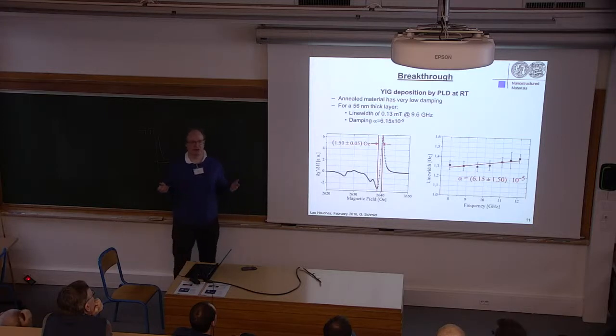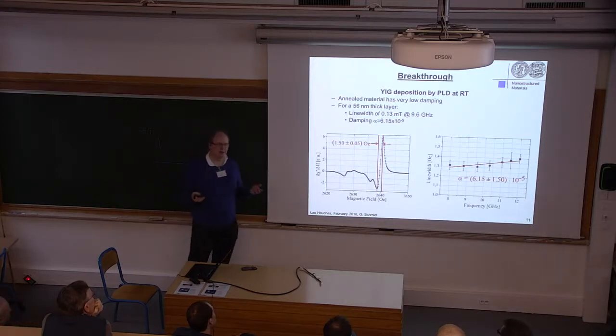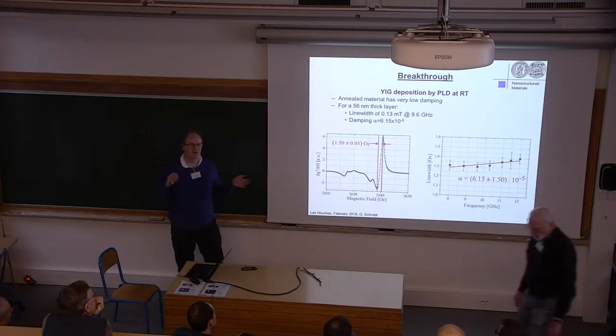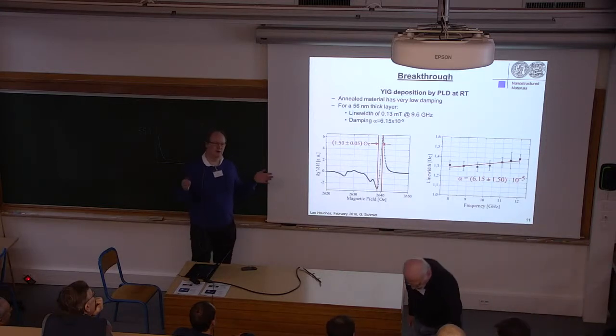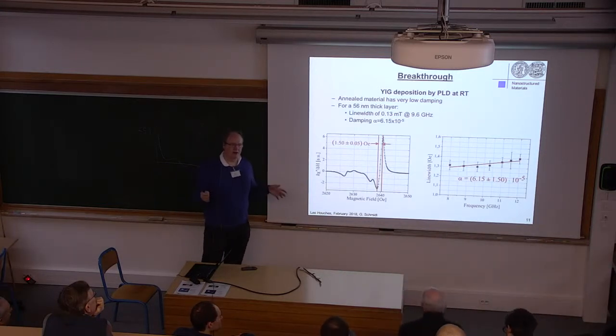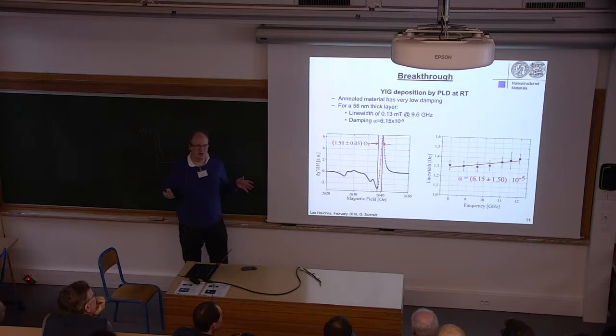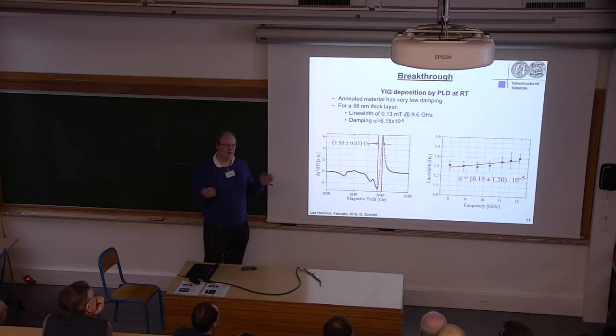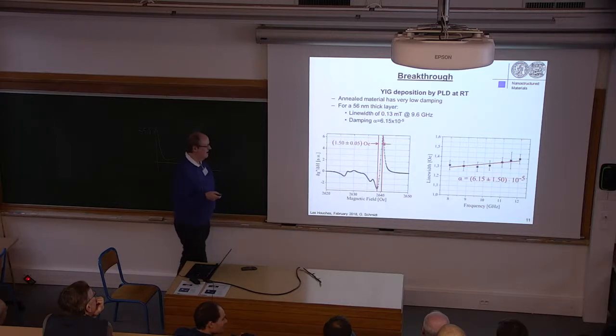So if you grow YIG at high temperature by PLD, you make thin films, you usually get into a range for the damping of, let's say, if you're good quality, then you have 4 times 10 to the minus 4. If you have very nice quality, you maybe get 3 times 10 to the minus 4, maybe even slightly below. And you usually have a line width of a few Oersted. So you're happy if you have 3 or 4.